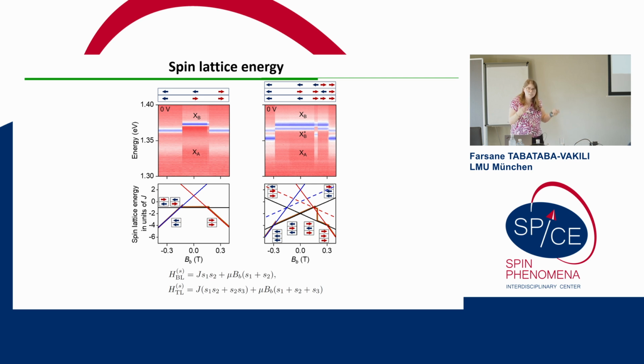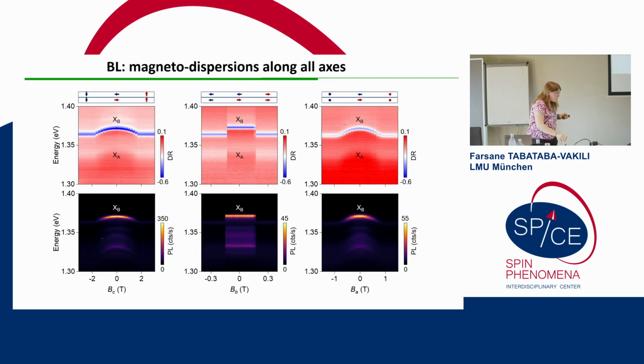So just to get a little bit of an intuition of why we have this intermediate state. Here I'm showing the bilayer with magnetic fields along the 3 different axes, as the material is anisotropic. So along the C-axis, we observe a spin canting with a saturation field of 2 Tesla. Along the A-axis, the intermediate magnetic axis, we observe a similar thing, but with a smaller saturation field of only 1 Tesla. And along the B-axis is the sudden spin flip transition with a critical field of only around 150 millitesla.